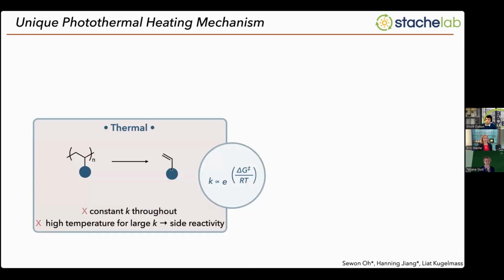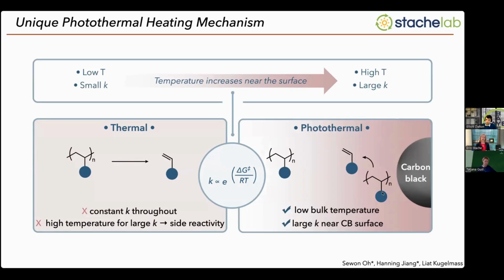And so again, just to remind you of photothermal conversion and the distinct heating mechanism from bulk pyrolysis. With bulk pyrolysis, there's a single rate constant. So you need to heat this up to about 500, 550 degrees C in order to induce depolymerization. And of course, other things are going to be happening as well, and so you tend to get a lot of side reactions. But in photothermal heating, only the polymers that are in proximity to the carbon black will start to break down and start to unzip and generate monomer, which is going to be expelled from the surface of the carbon black, whereas the overall bulk temperature is much lower than the surface temperature of the carbon black. So you get a much faster rate of depolymerization and should get a much cleaner product distribution, as well as being able to use photons as opposed to standard electrical heating methods.